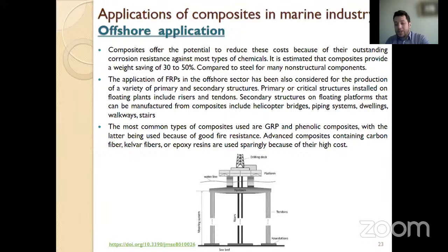Regarding the application of composites in the offshore industry, composites offer the potential to reduce the costs of oil and gas production because of their outstanding corrosion resistance against most types of chemicals. It is estimated that composites provide a weight saving of 30 to 50% compared to steel for many non-structural components. The application of fiber-reinforced polymers in the offshore sector has also been considered for the production of a variety of